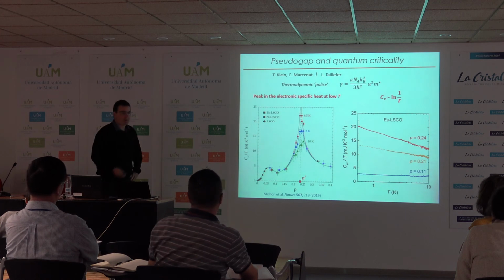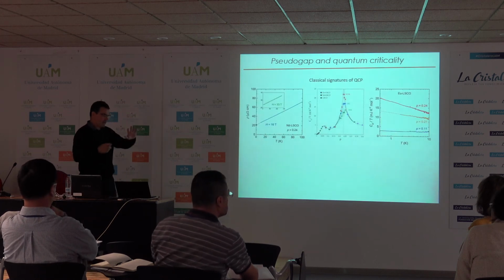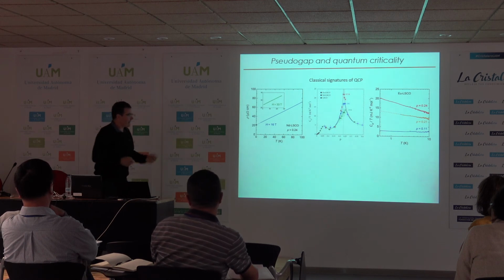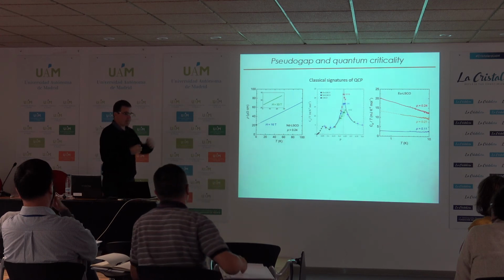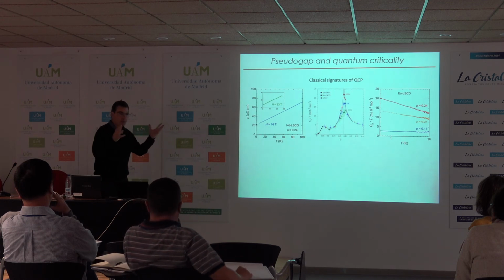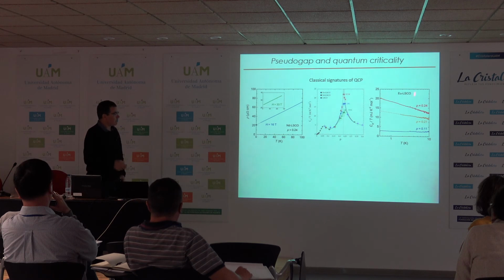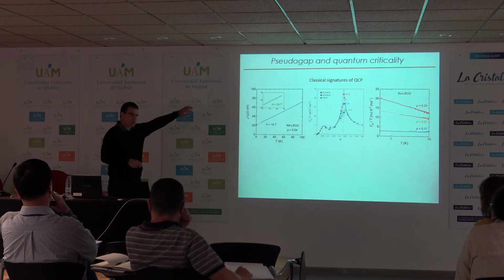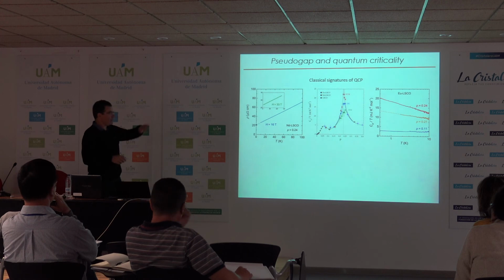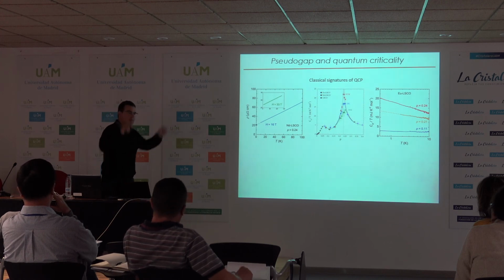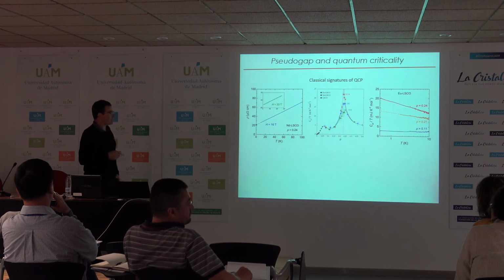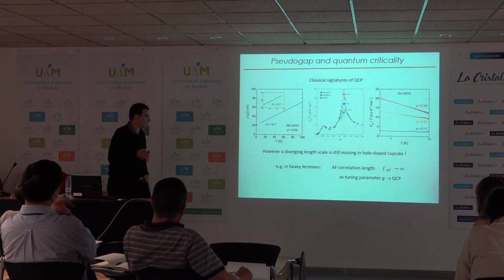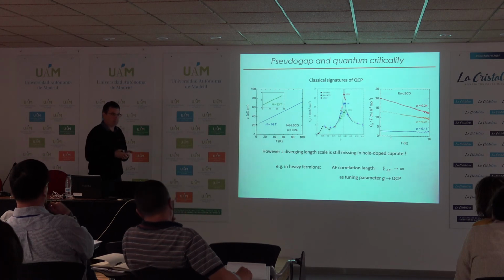I was actually going to answer your question maybe, because okay, very good. It seems that we observe classical signatures of a quantum critical point. But as I said for the resistivity, there is an anomalous range of doping where linear resistivity is observed. As you point out, at the critical point it should remain linear down to very low temperature, right? But as soon as you are away from the quantum critical point, this should come back to a more Fermi liquid-like behavior. Which is not the case here, you are right. So in fact, there are classical signatures of a quantum critical point, but a diverging length scale is still missing.